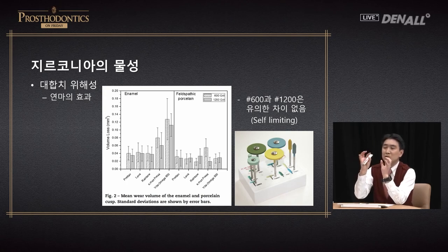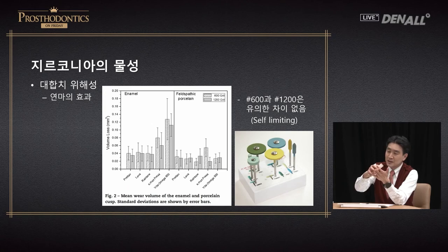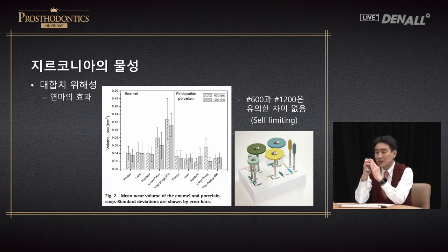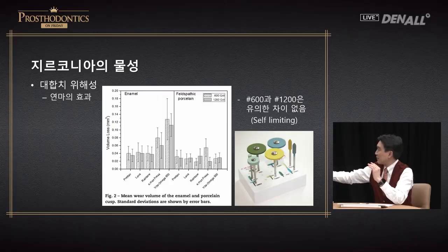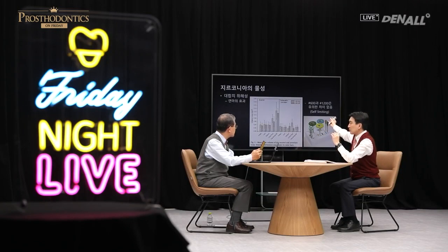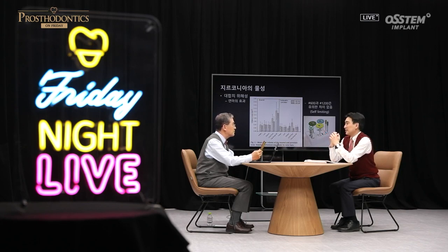This rough surface at the very early stage does have impact on wear, but this also goes through wear. And once this rough surface is worn, the roughness itself is not important, and depending on the characteristic of the substance, the level of wear is determined. In the test, using sandpaper 600 and 1200, no statistically significant difference was observed, regardless of whether you do 600 or 1200. There was slight difference, but there's no statistical difference.